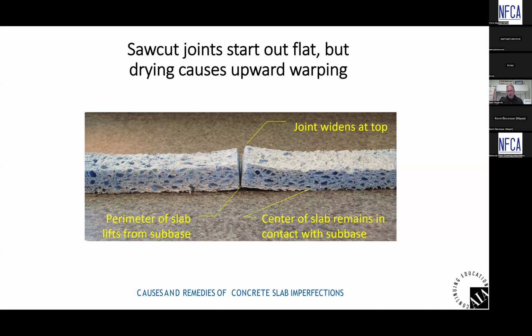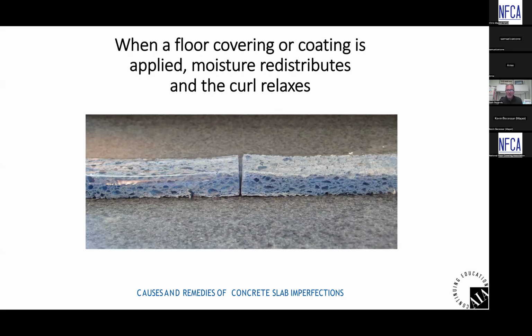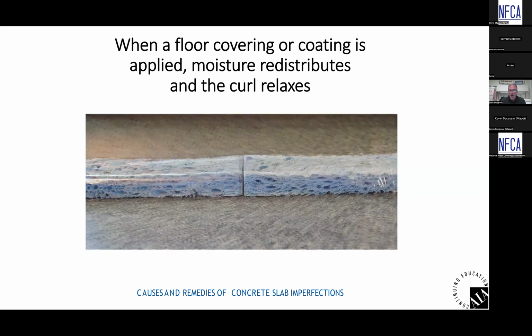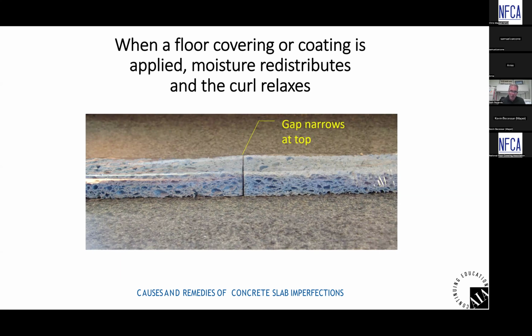So you have two concrete slabs that have a little bit of curl to them, and you install sheet vinyl over top of them. What we did here may be kind of hard to see, but we took clear plastic wrap, which acts like a finished floor covering, and we laid plastic wrap over these curled sponges. We just let them sit there and we time-lapsed it. And what we saw happen, which happens to concrete, is the moisture redistributes throughout the sponge and that curl that was once there relaxes. And now, as you saw in the time-lapse photography, the joints at the top of the slab, or the top of the sponges, if you will, have gotten closer together as that moisture redistributes and the sponges relax. This happens to concrete.